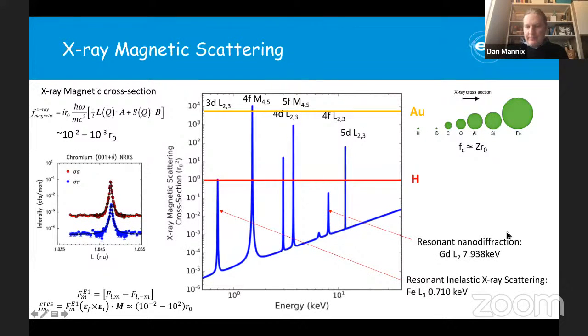What we've done in this work, the first part, is this resonant nano diffraction, and we've been working in the hard X-ray regime at these resonances at the gadolinium L edges. The reason we've been doing that is because we need to do diffraction. This has been key to our work. These gadolinium iron garnets don't give any Bragg reflections at all in the soft X-ray regime. So if we were working at the iron edge or the gadolinium M edges, we wouldn't see any Bragg peaks at all. We wouldn't be able to do diffraction. So this was not available to us for this particular type of system. We have to work in the hard X-ray regime at these energies.